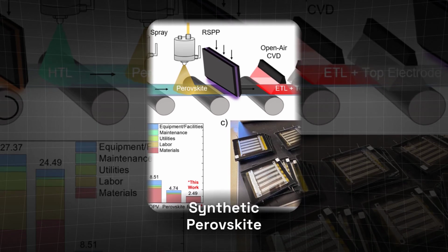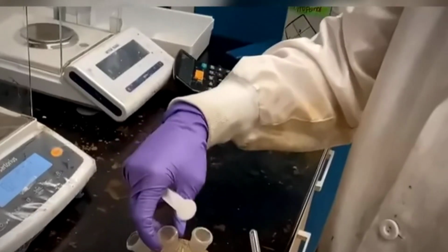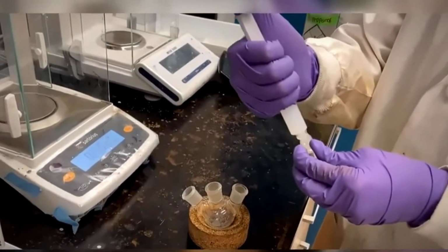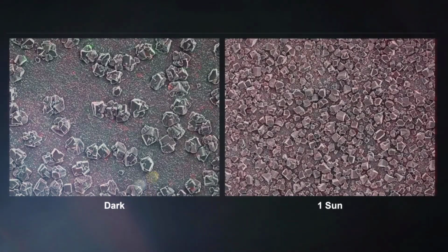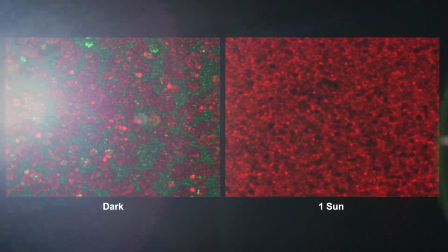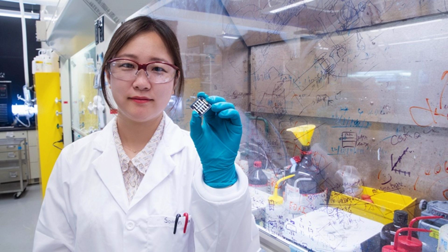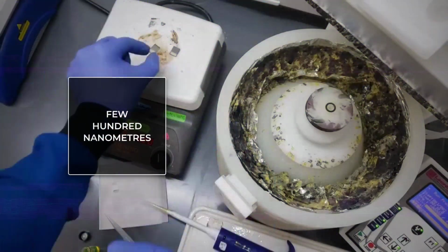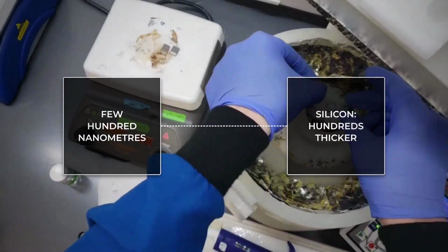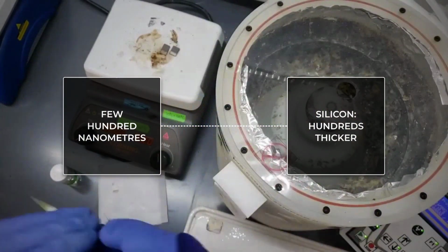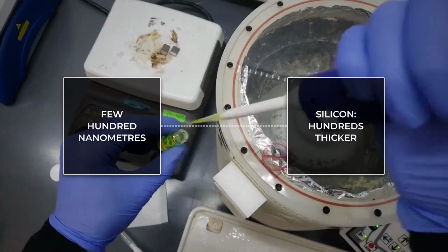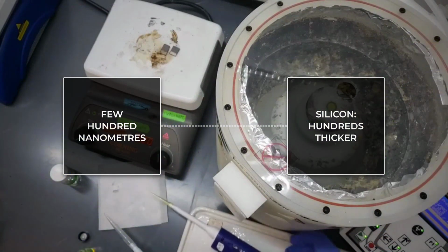Chemists worked out they could build entirely new compounds copying that arrangement out of cheap common ingredients plus a small amount of lead. And that pattern turns out to be extraordinarily good at one job. It absorbs light roughly 10 times more strongly than silicon does. That single fact changes everything downstream. A layer a few hundred nanometers thick, thinner than a soap bubble, absorbs about as much sunlight as a silicon wafer hundreds of times thicker.